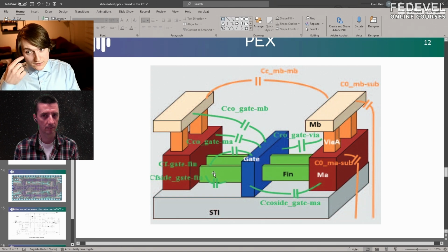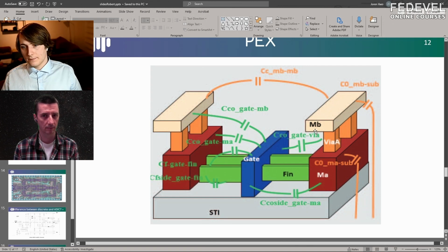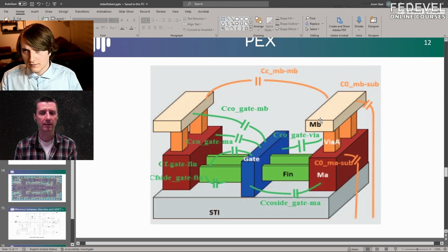And what makes a big difference as well is the thickness of the metal. So you draw the width, right? But on one wafer, the thickness is 40 nanometers, on the next it's 37, and it's 45. And so that also results in variability. But I don't know exactly how, I don't have a quantifiable value for that.